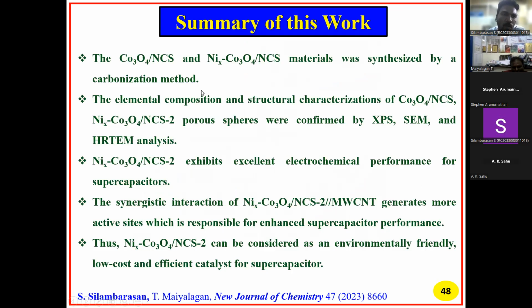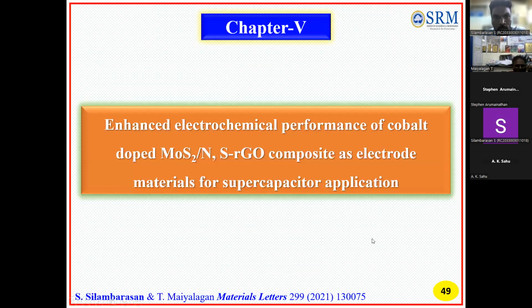Next, the summary of this work: the cobalt oxide and nitrogen-doped carbon sphere and nickel-doped cobalt oxide and nitrogen carbon sphere were synthesized by the carbonization method, and the elemental composition and structural characterization were confirmed by XPS, SEM and TEM analysis. This sample is expected to give good electrochemical performance, and the synergetic interactions of the two-electrode system generate more active sites and respond to the enhanced supercapacitor performance, considering an environmentally friendly, low-cost and efficient catalyst for a supercapacitor.